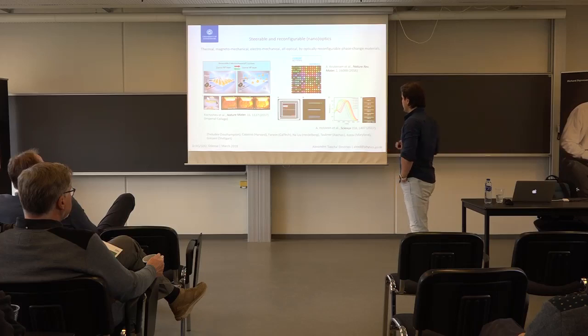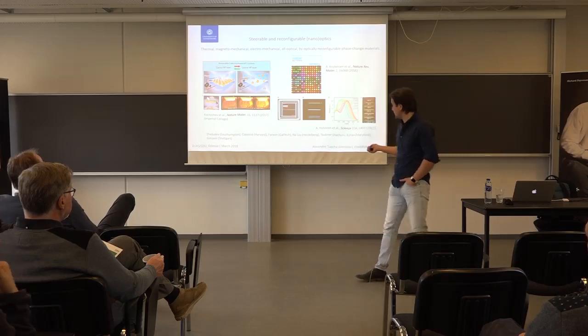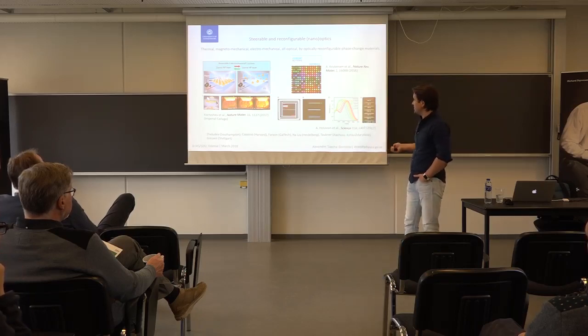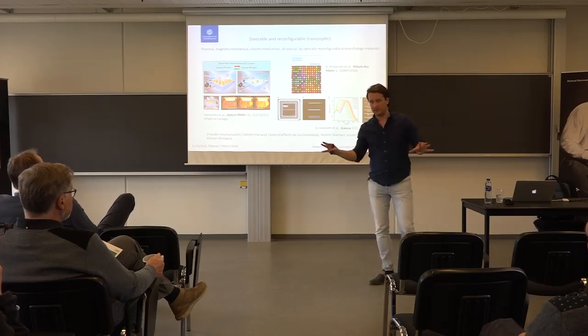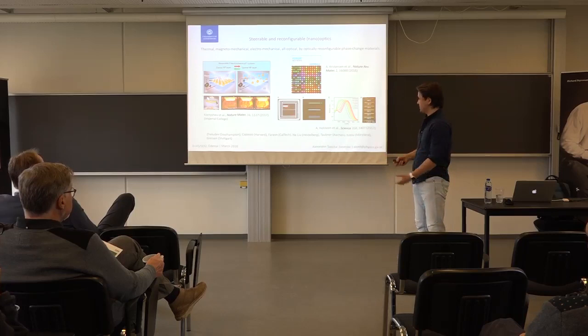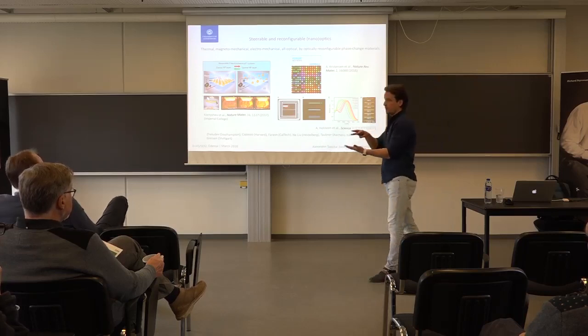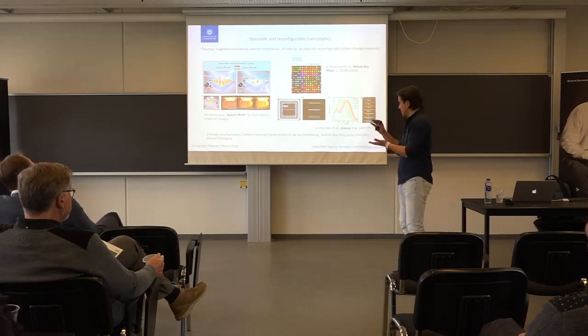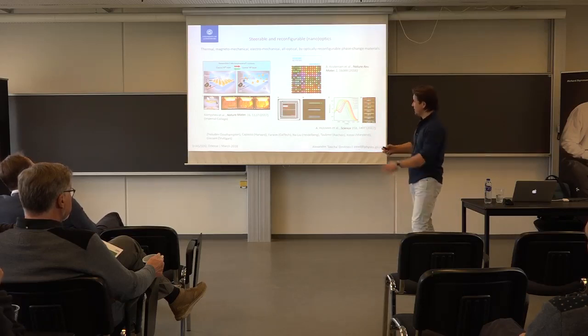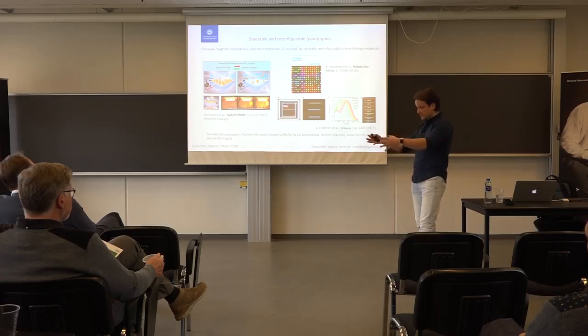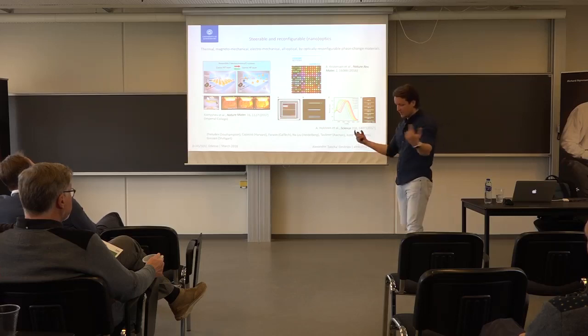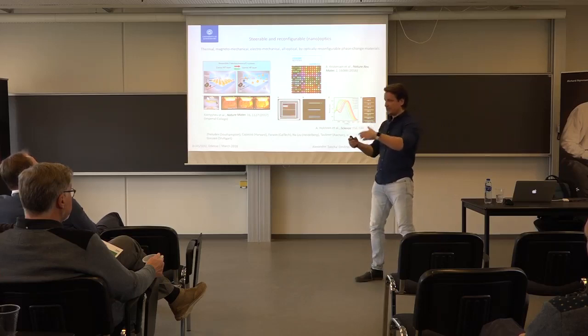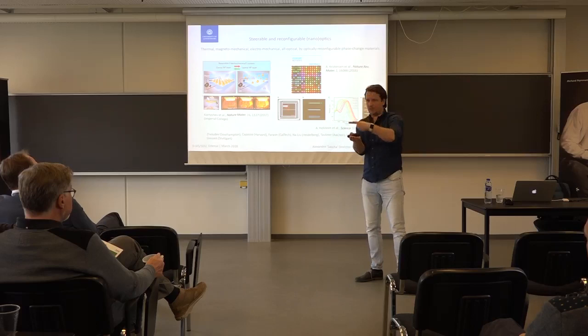One of the very recent examples is actually the work from the group where I spent my sabbatical at Stanford, Mark Brongersma. And in this case, it's actually not even plasmonic, so there are no metals there. It's silicon nanowires positioned in front of an aluminum mirror. And just by tuning into different resonances, there are different kinds of resonances, electric, magnetic, at different heights. So they built, Aaron is the first author of that paper, he built this MEMS sort of frame that is able, by applying a magnetic field, to slightly bend. So essentially your wire is walking up and down.